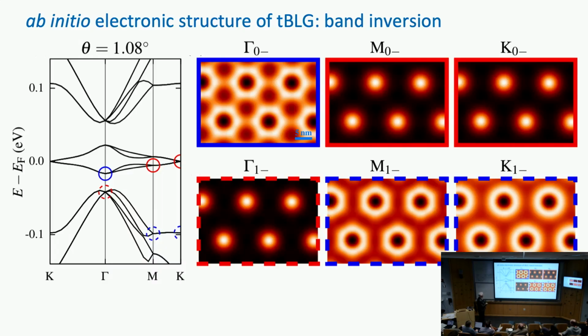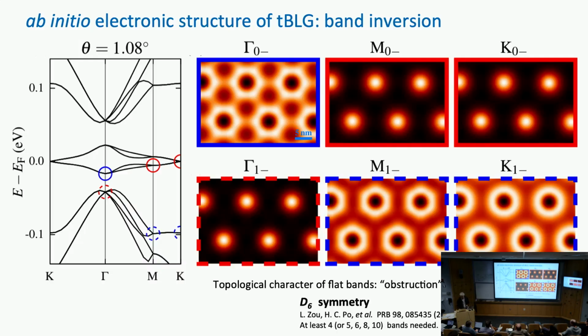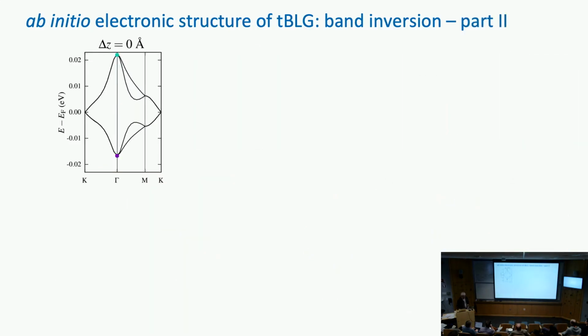Now, if you calculate the derivatives of these states with respect to k, you will find a non-trivial contribution to the geometric tensor that I was describing. So that's where this comes from. And it's very clear from these calculations. Moreover, we see something even more exciting. So this now is a different set of states that I'll show you.